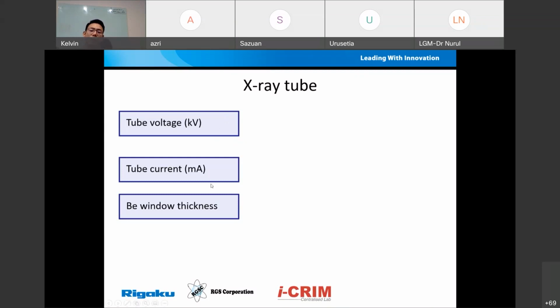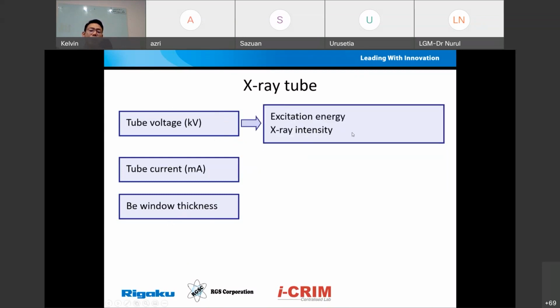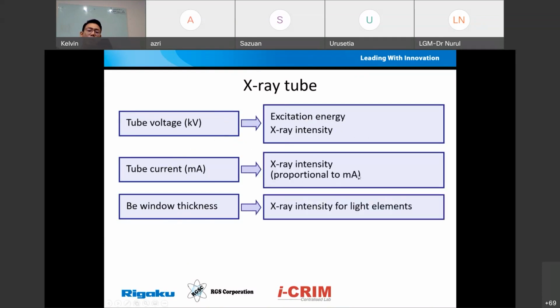So three things are important for the tube. The first is the tube voltage, which generates the excitation energy. The excitation energy determines which line you can generate, either K alpha or L alpha and so on. And also the tube current itself, which is proportional to the X-ray intensity. So if you want a higher intensity in terms of count, then you can increase the tube current.